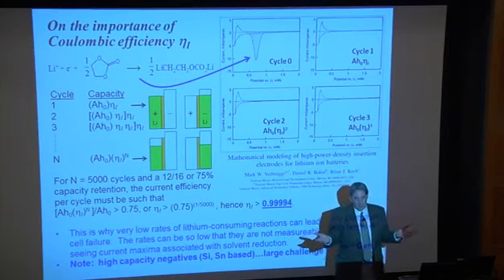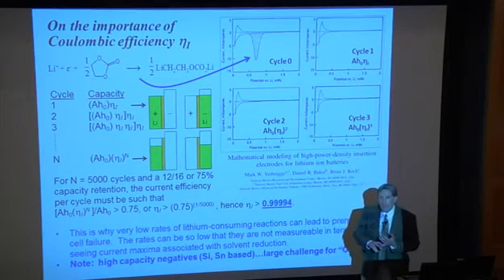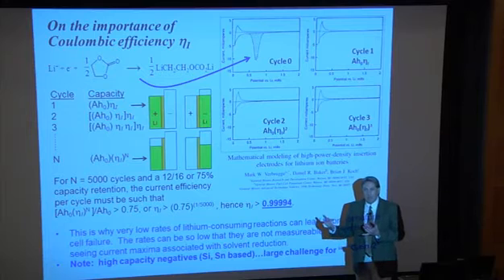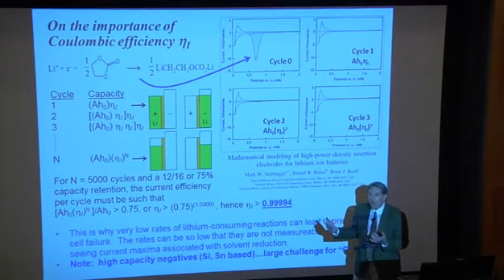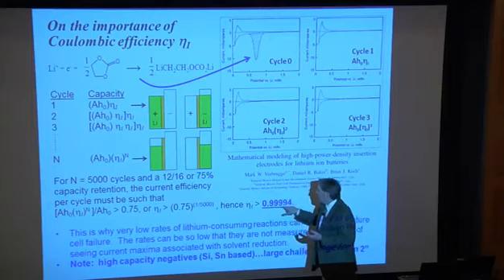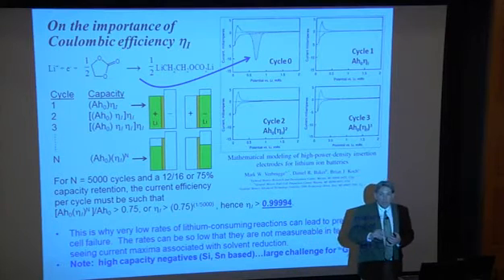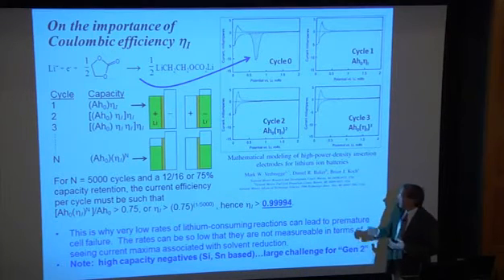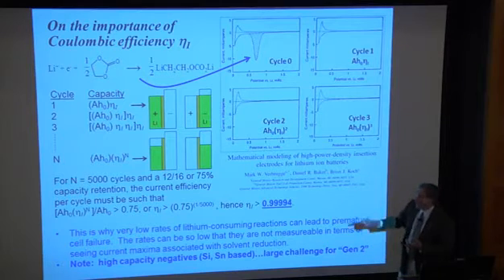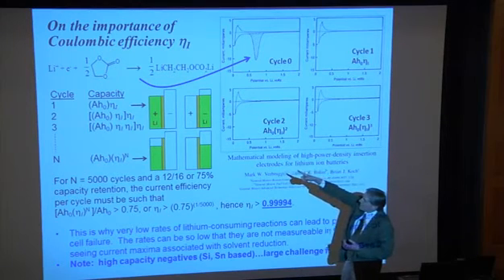So you can solve to say, okay, if I want, for example, in a Chevy Volt application, we need 5,000 cycles. And I don't want to go less than 75% of my nominal capacity. What's my current efficiency have to be? You find out it's got to be super high, 0.99994. And that's why you can't see anything there, but that reaction listed up there is consuming lithium.